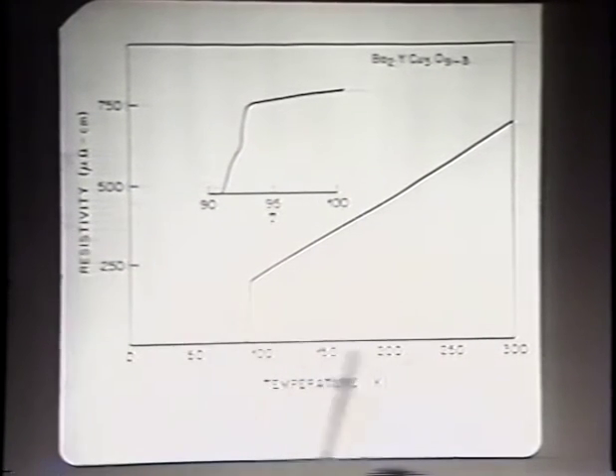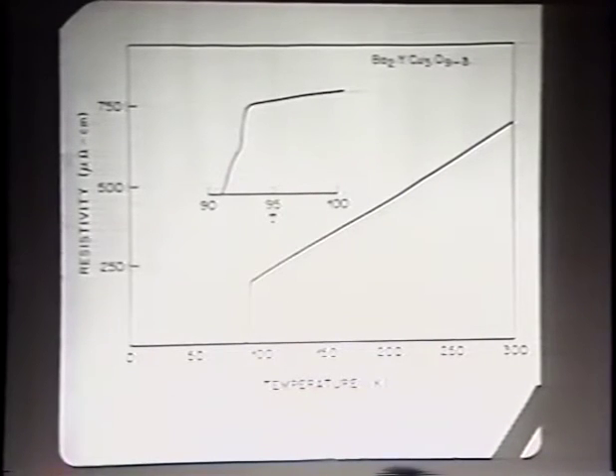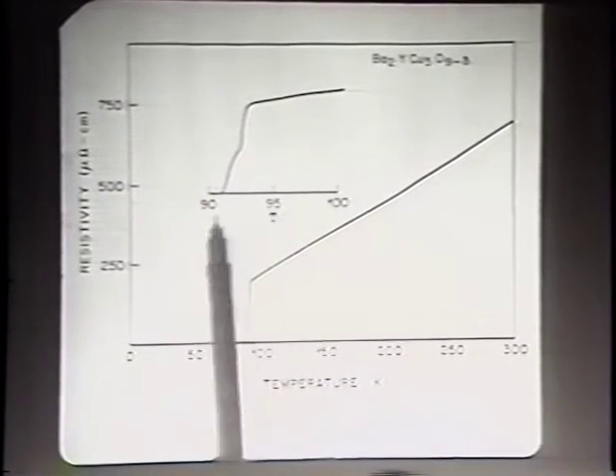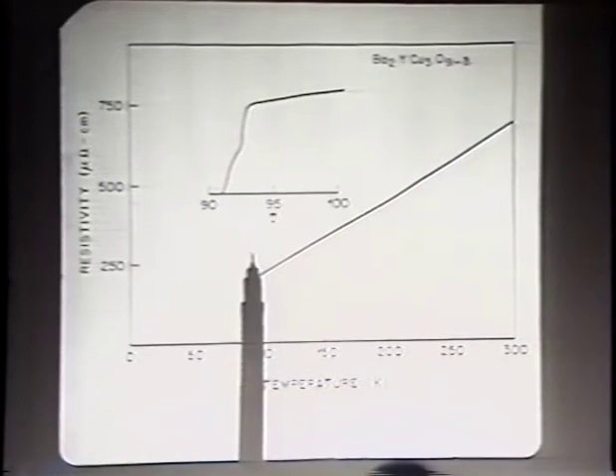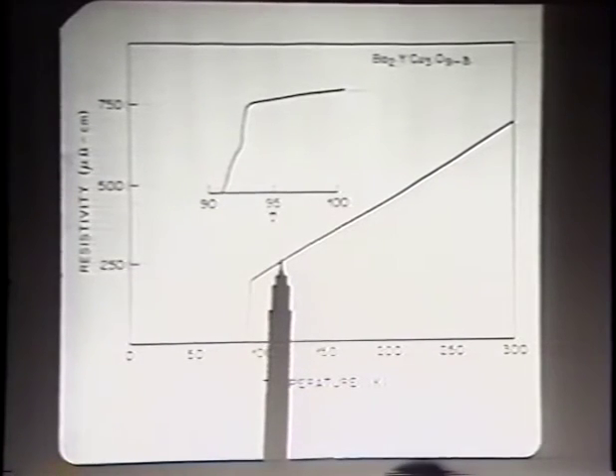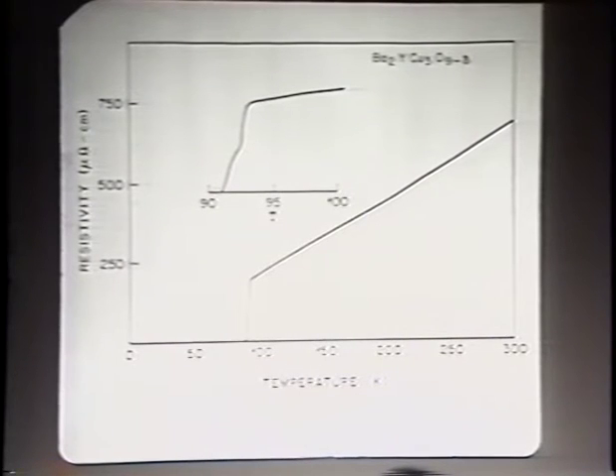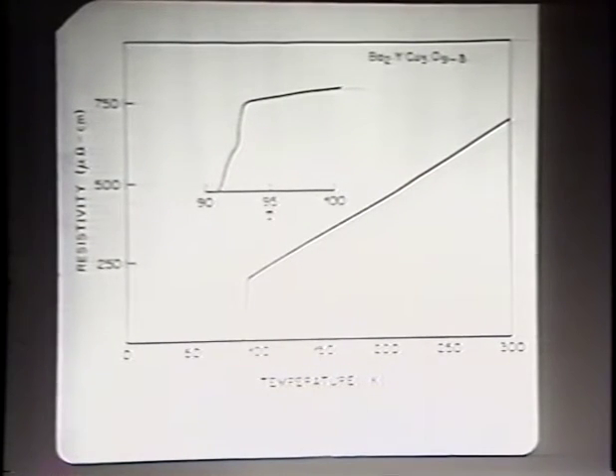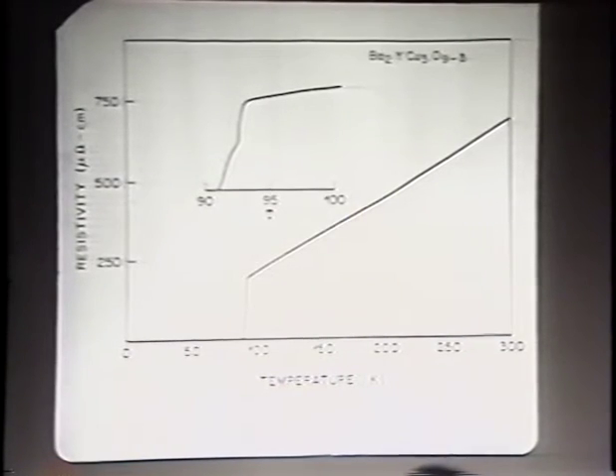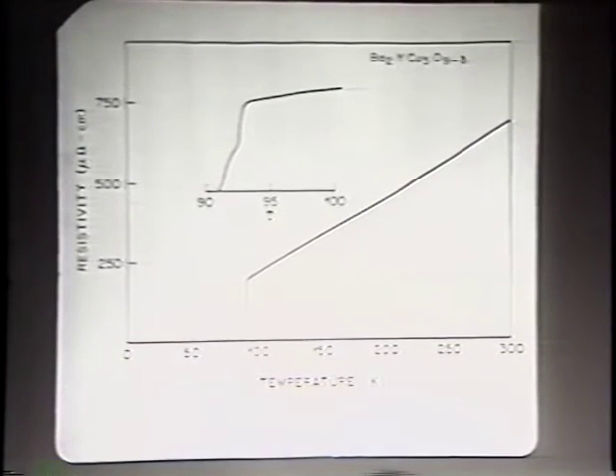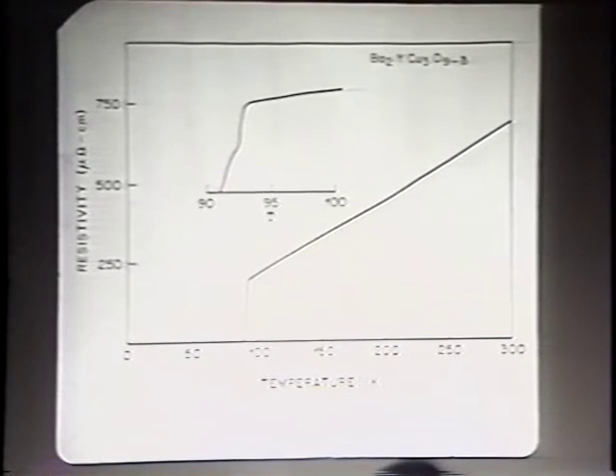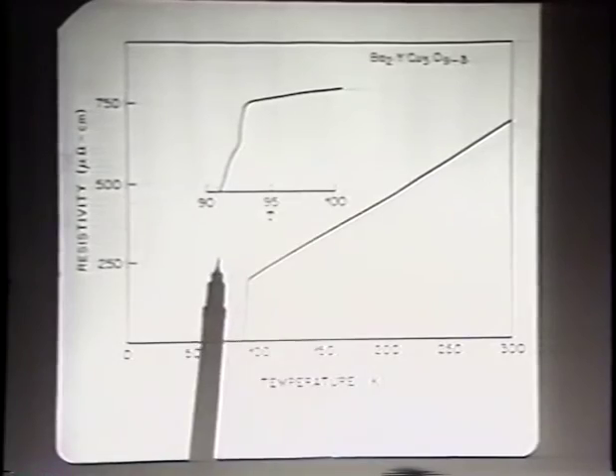This linearity in resistivity, together with the very unusual optical properties that Bornstein, Gordon Thomas, and Doug Rapkin measured in our lab, which I don't have time to show, and also the fact that in the normal state this material has a considerable Curie-Weiss contribution to the susceptibility, all these 3 facts together make us believe that these are not ordinary metals at all. And these are taken as ingredients to some theories, and we'll have a talk later tonight, which invoke unconventional pairing, meaning non-electron-phonon pairing, leading to superconductivity. That's one aspect. Of course, these are measurements on phase-pure material, and there's absolutely no second phase whatsoever there, undetectable in X-rays.